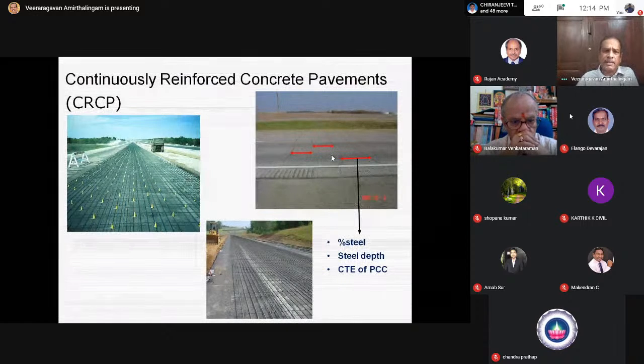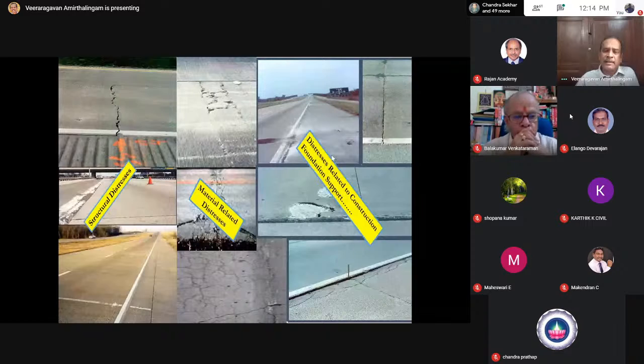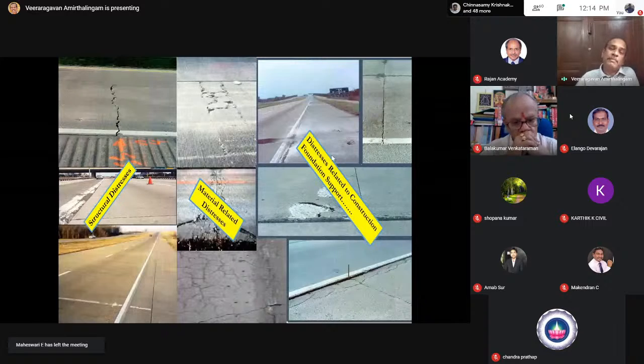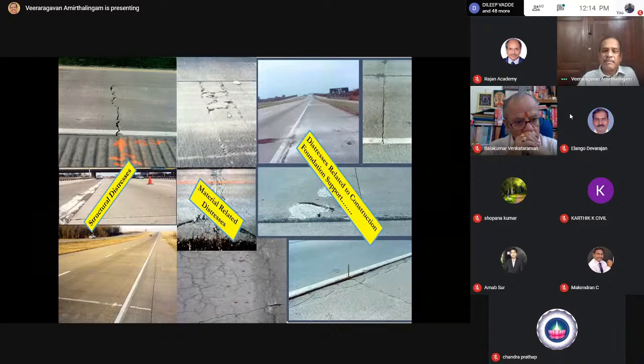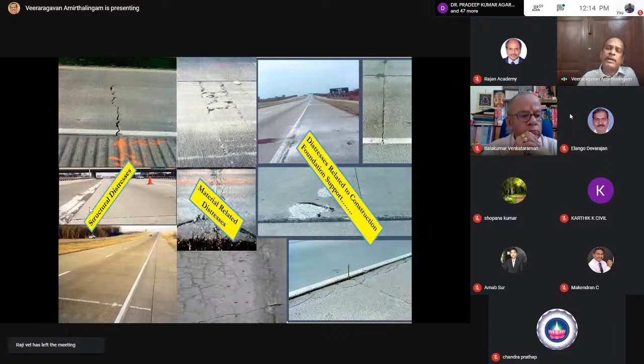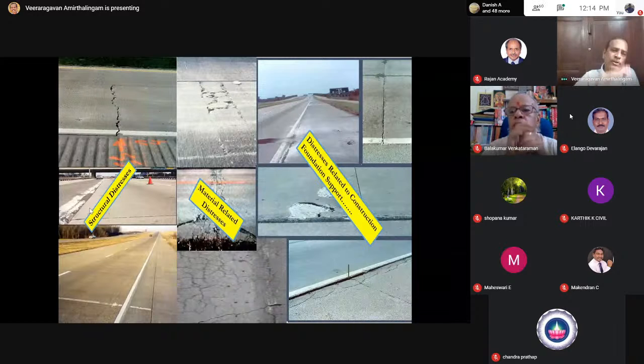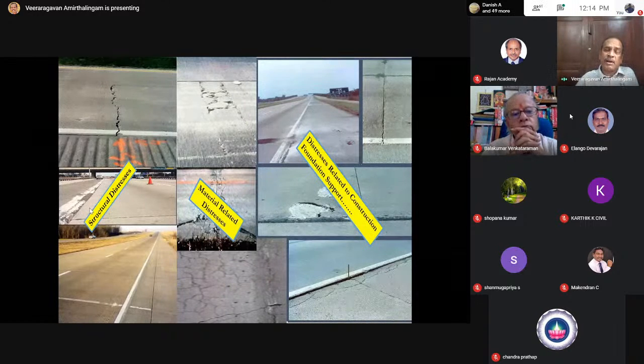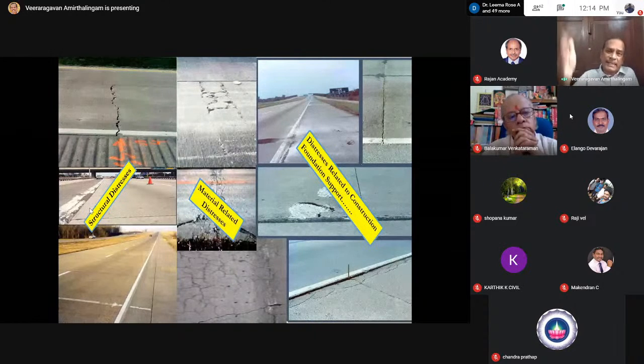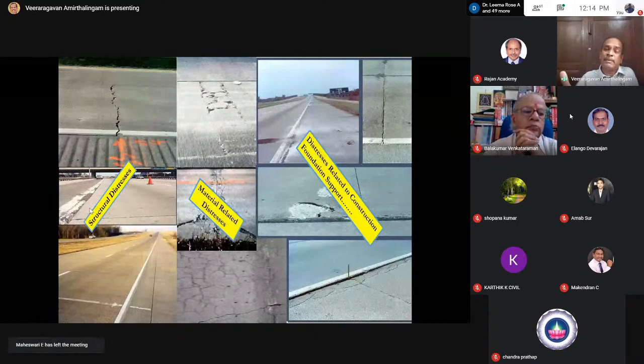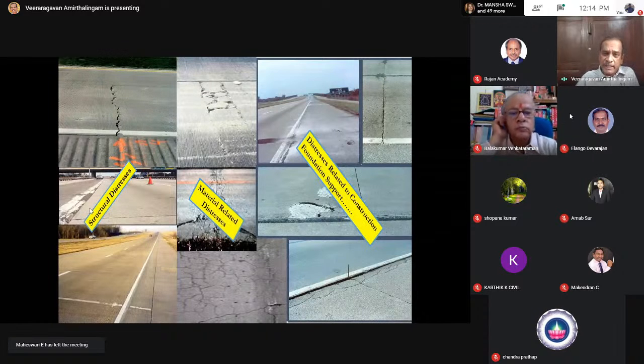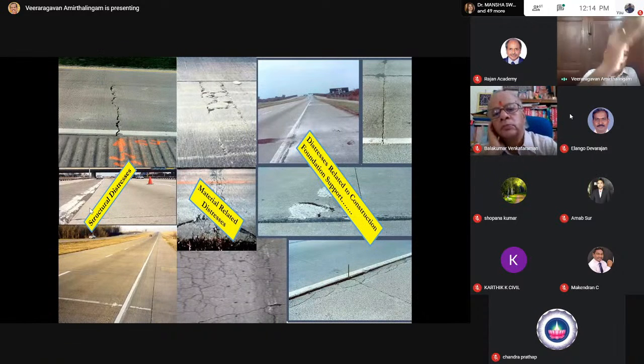It's possible here. The issue at this point of time is: will the pavement last for 30 years? May or may not. Why may it not? Because distresses can be material related. There can be cracks mainly related to material durability issues. There can be structural distresses. If you have not provided the joints at every 4.2 meters or 4.5 meters, then the crack will form exactly at 4.2 or 4.5. Or these joints should be cut to 1/3 the depth using diamond cutters between one day to second day. If you delay it, the cracks will form randomly.